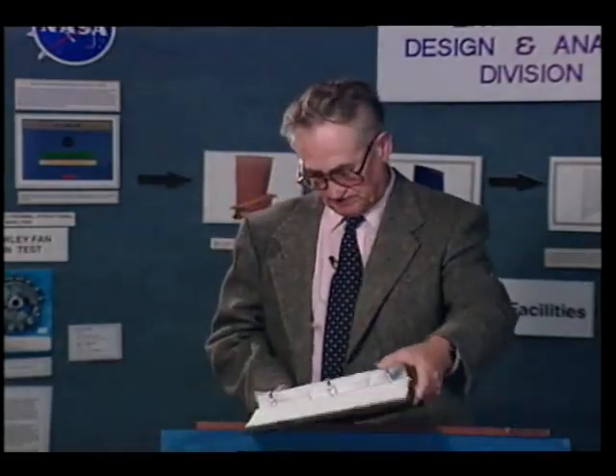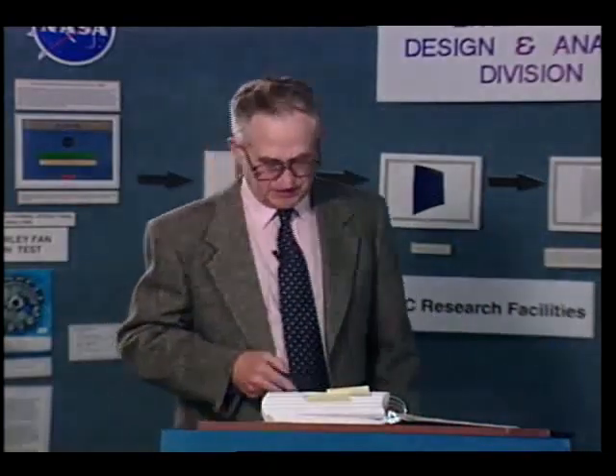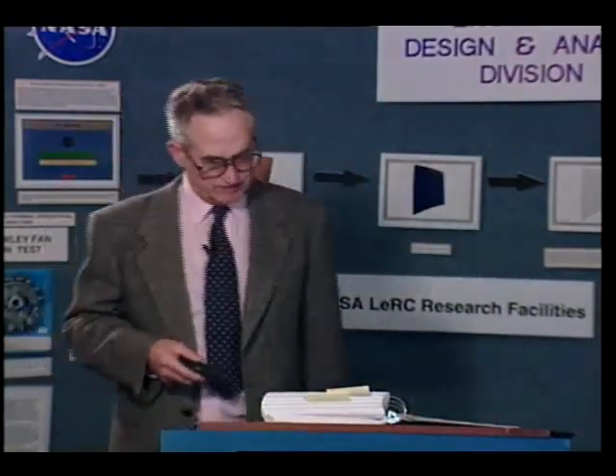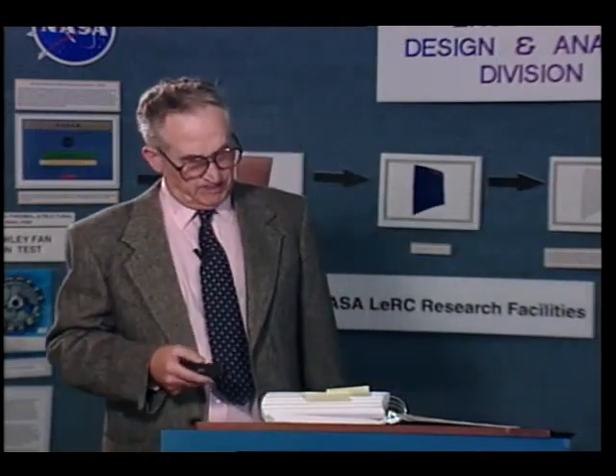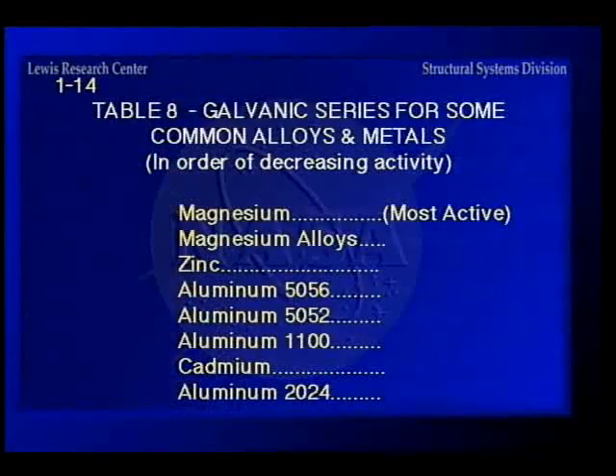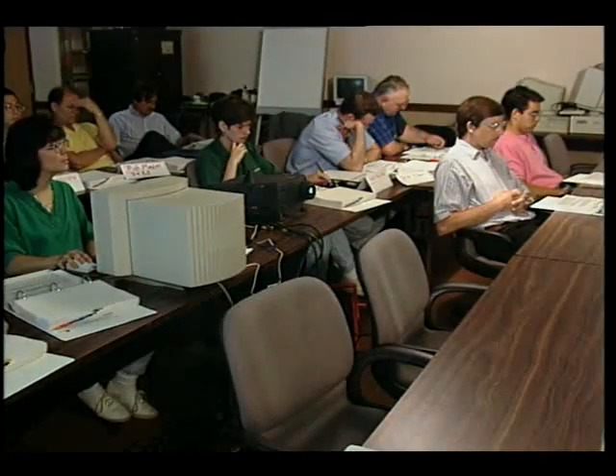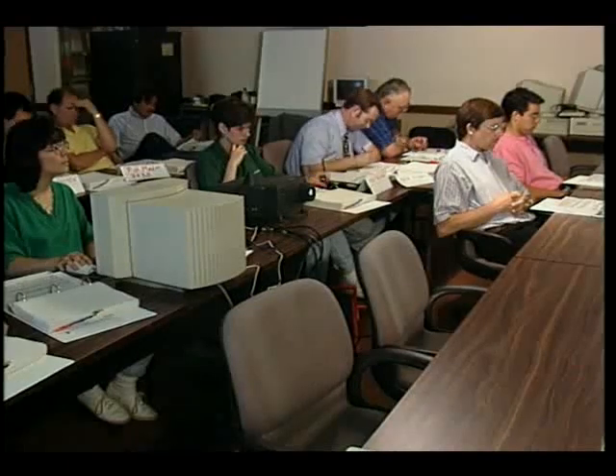Now here is the table of the galvanic series, and this is something you can find in Mark's Handbook and various places. One of the things I wanted to point out in this is that if you look at cadmium over here, it is right in the aluminums. Also, zinc is there. So if you use a cadmium plated fastener in aluminum, you will get less galvanic corrosion than you would if you used one of these down here, like a brass or copper or Inconel or something like that.